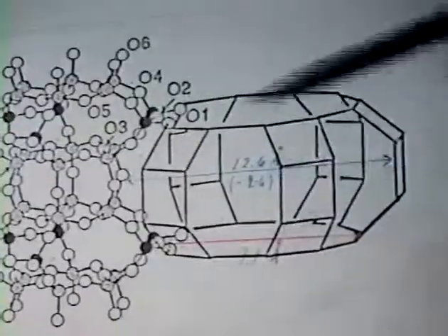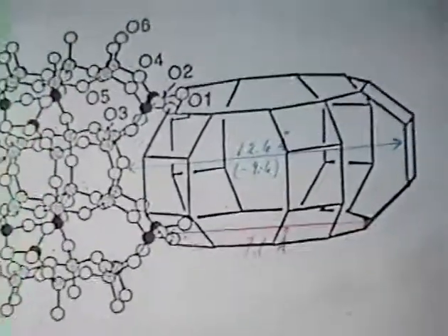But it is about the right particle size if you think that what's happening is that these catalysts, which are prepared by ion exchange, grow until they sort of fill the cavity and then they stop. Because where they ought to stop is about 12 angstroms. This is one cavity in the parallel pore of the catalyst. This very small 6-membered ring, and this little small cage, and this one are the cancrinite cages. And the entrance in these undulating pores are about 7 angstroms, and the large pore here is about 12.6 angstroms.